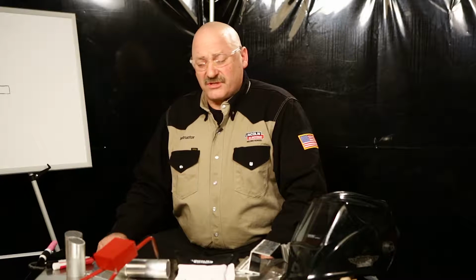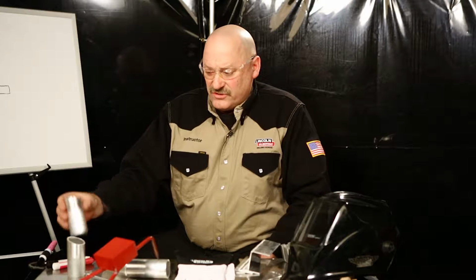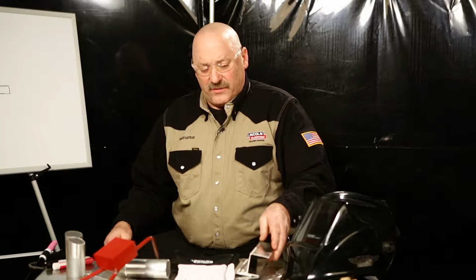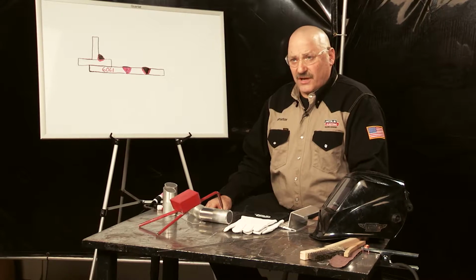Today we're going to be talking about cracking in aluminum welds, and particularly when we're welding on the 6 series aluminum alloys. 6 series alloys are predominantly used as extrusions, also as plate, and when we weld on those, we weld them with a filler metal of a different composition than the base metal. We usually weld them with either a 4 or a 5 series filler metal. And it's very important that we get adequate dilution of the filler metal in order to prevent solidification cracking on